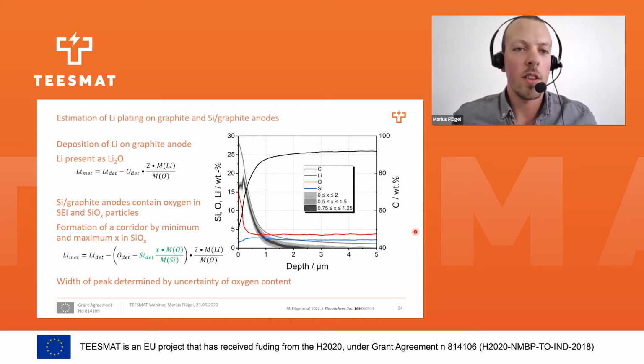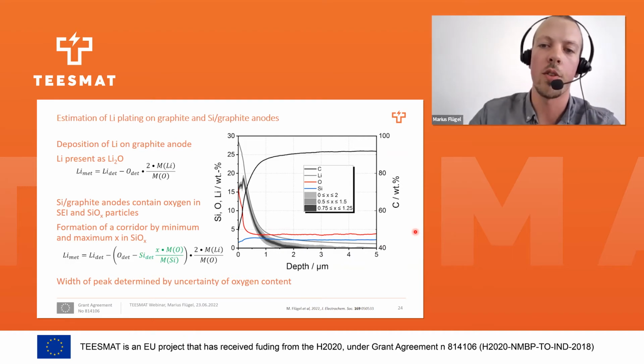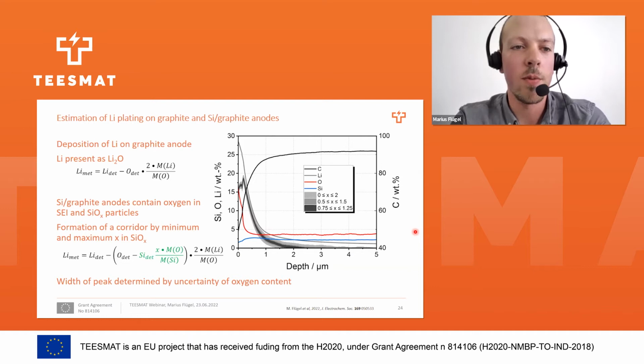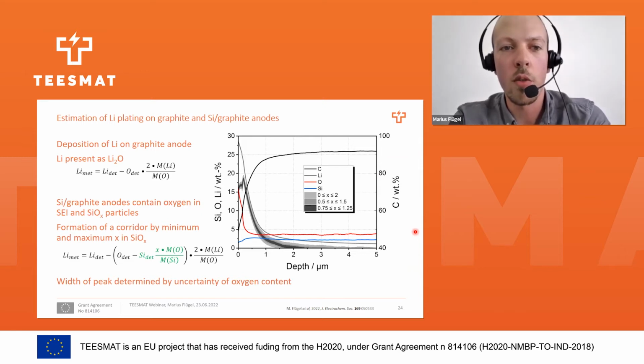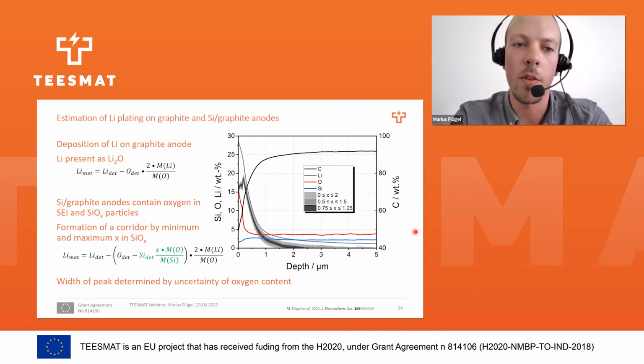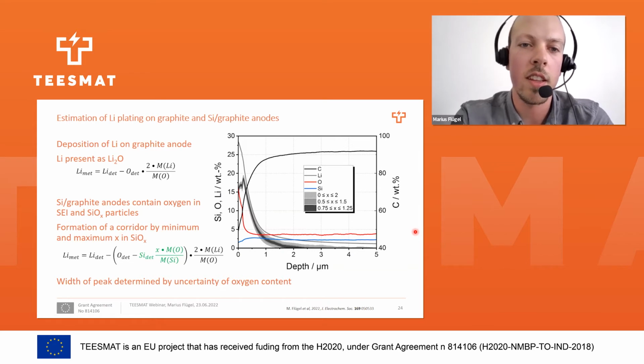Recently, we've developed a technique to quantify the minimum amount of lithium plating on top of the surface of the anode. For this, we assumed that lithium in the SEI is only present as lithium oxide. Why lithium oxide? Lithium oxide has the highest percentage of lithium of all SEI species. To calculate the maximum amount of lithium oxide in the anode, we use the detected amount of oxygen, and any lithium that is present and not bound as lithium oxide has to be metallic lithium.